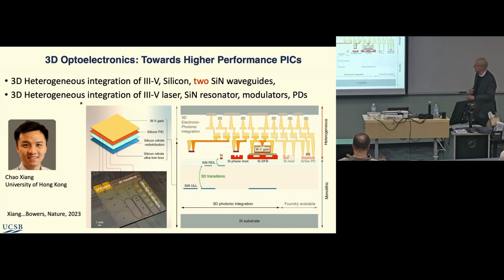I don't know that you really need 2 layers. We were doing this because when we fabricate all the laser processing, we were degrading the Q of the silicon nitride. So we'd start with a Q of 400 million, and by the time we're done, in fact, these results, the Q is about 40 million. So we stopped putting them up here, and we buried them underneath microns of SiO2, and we're still seeing the problem.